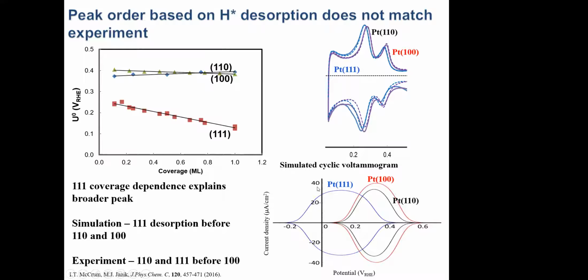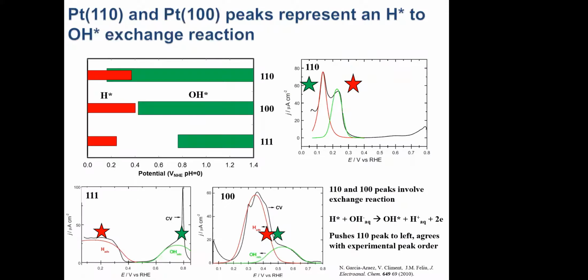And this should have been an easy question for DFT. Single crystals, simplest adsorbate you can put on a surface. And we can't get the thermodynamics of it going on and off the surface right. And that's because that process is not actually hydrogen going on and off the surface. So I don't know how many people here are long-trained electrochemists, and maybe like me, the first thing that they learned in electrochemistry was the platinum CV and the butterfly. And I learned that those peaks were hydrogen coming off and on, and that's what's in the Bard-Faulkner textbook.